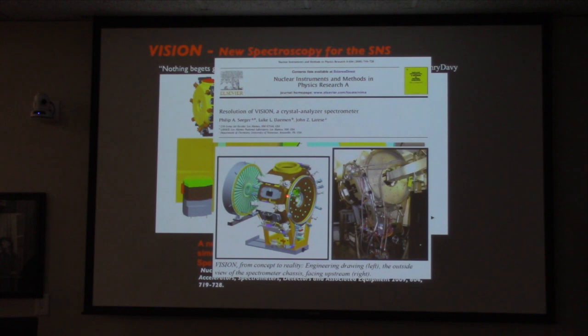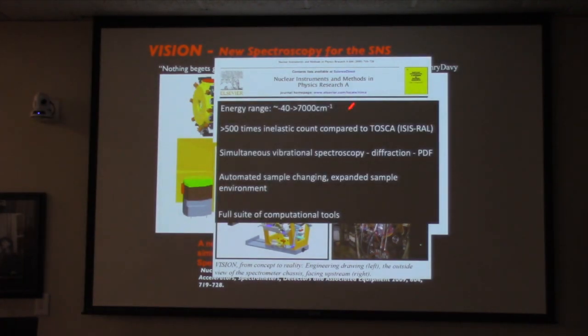It can do diffraction, inelastic scattering, and what's called pair distribution function analysis. And it turned out to have the best pair distribution function analysis in the world. Here are the comments. It's 500 times higher throughput than the best instrument in the world. It's actually 1,000 times better, but if you don't want to have what's called frame overlap, where the fast neutrons from the next pulse catch up with the slow neutrons from the other pulse, you have to operate at 30 hertz, unlike the 60 hertz at the SNS. So for certain experiments, it's 1,000 times faster.